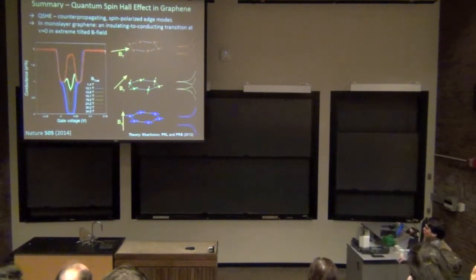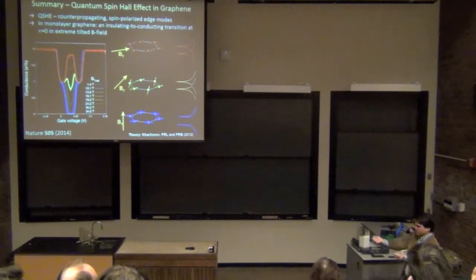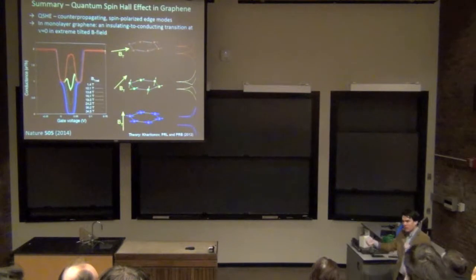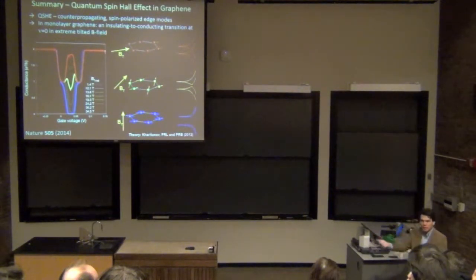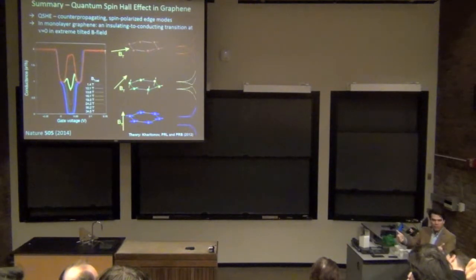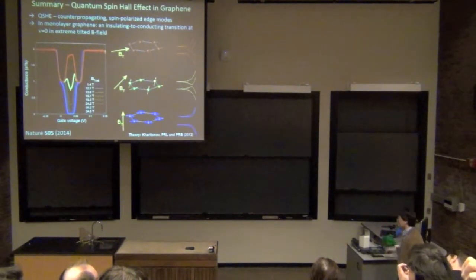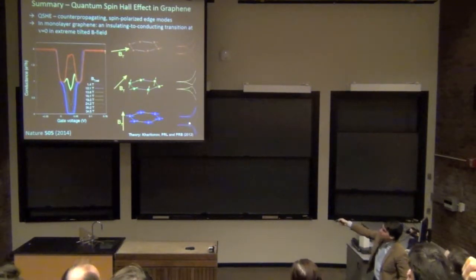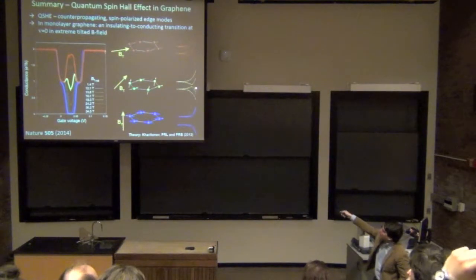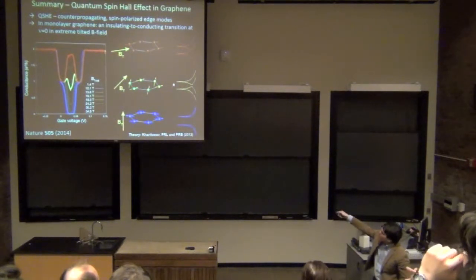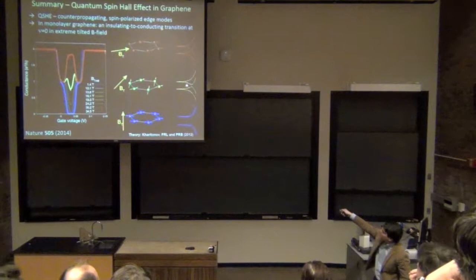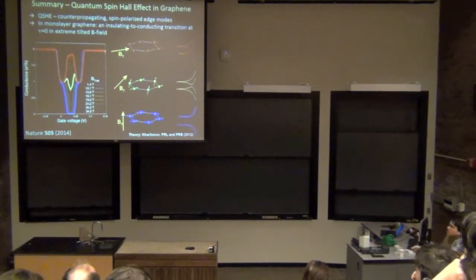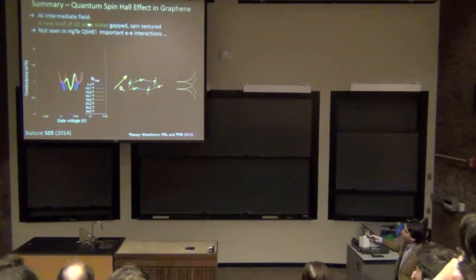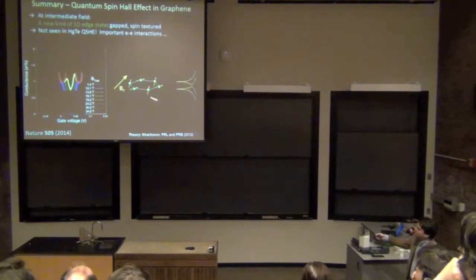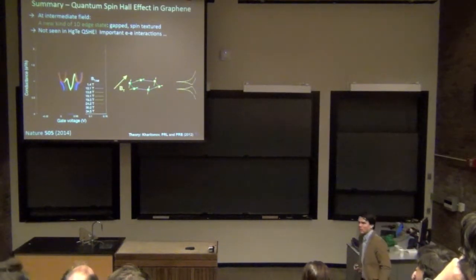And in the intermediate state, what we're seeing is what's known as a canted antiferromagnetic state. You can imagine this play between the Zeeman energy, which wants to do this, and the antiferromagnetic energy, which wants to do this. So we have some state in the bulk that has these canted spins. And the edge state signature of that is something intermediate between this gap state and this quantum spin Hall state, where we have a tiny gap at the edge, but just by moving the Fermi energy up or down slightly, we can see the edge states of this canted antiferromagnetic state. And that's nice because this is a new kind of one-dimensional edge state. It has a gap, it's spin textured, and it's due to electron-electron interactions in the system.